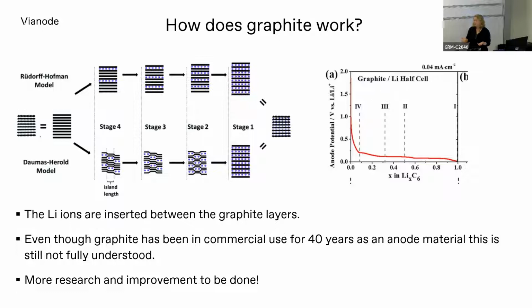Every time you rearrange the chemical bonds in a material, you have the risk that the bonds don't go back to the way that they were at the beginning. And then that means that, even if you have 99% of your bonds go back to the way that they were at the beginning, a lithium-ion battery is considered to hit end of life when you have 30 to 40% of the capacity gone. So then you're only talking about you losing 1% of your capacity with every cycle. And then all of a sudden you're at 30 cycles, 40 cycles. So you can imagine how efficient the reaction has to be in every cycle in order to get the required life that you need for an EV battery. When you buy an EV battery car, it's expected that you could charge and discharge that battery 2,000 or 3,000 times before it hits end of life, which means that that reaction needs to be incredibly stable. And that is why graphite is the dominant anode material, because it is able to work in that way.